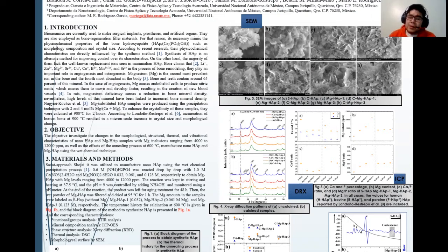Figure 3b exhibits the magnesium content in parts per million for all samples. Magnesium concentrations are between 3,626 and 11,205 parts per million. It is worth noting the magnesium H-MgHAp-1 samples, which exhibit the closest magnesium contents to the samples reported by Landeros-Restrepo.